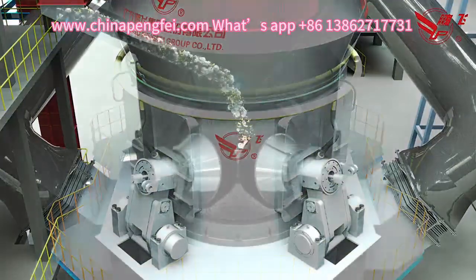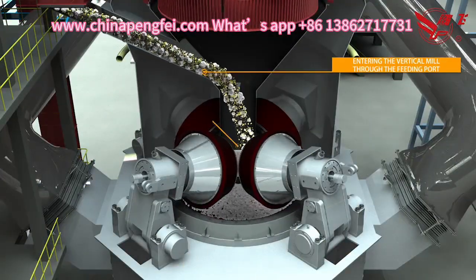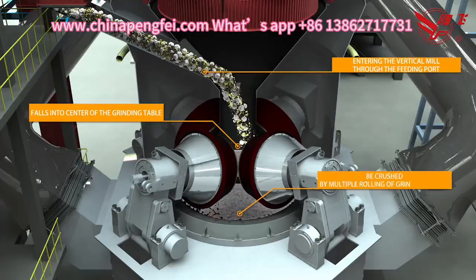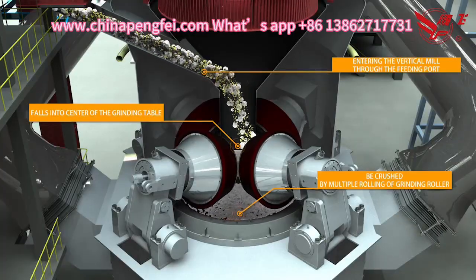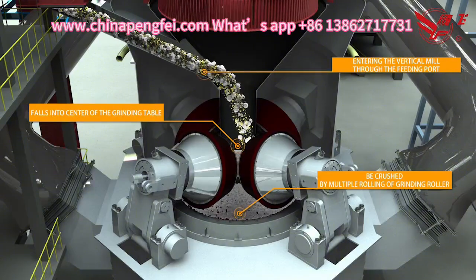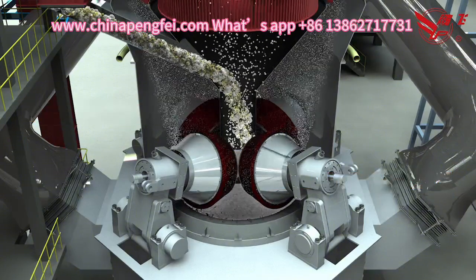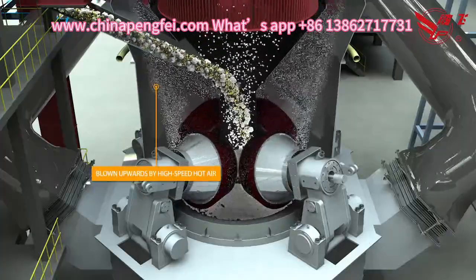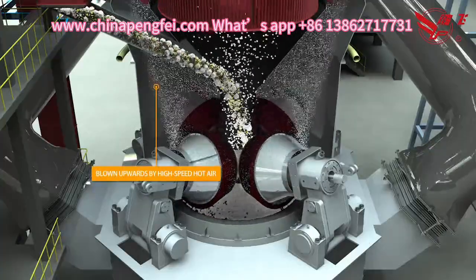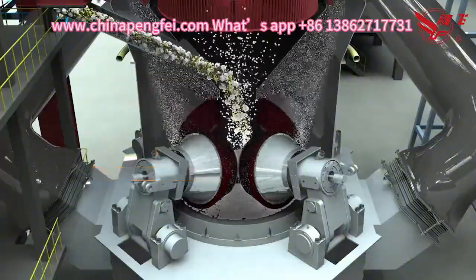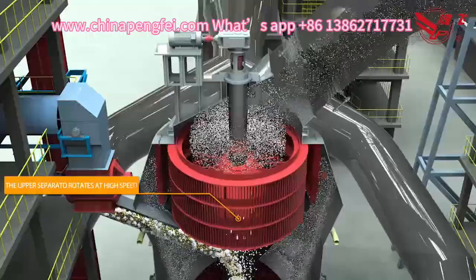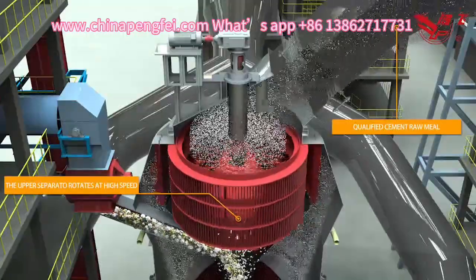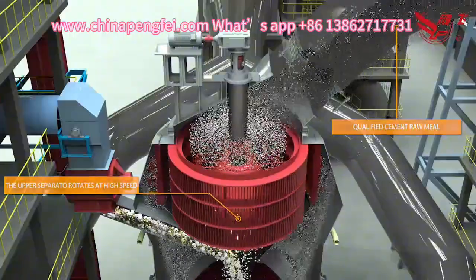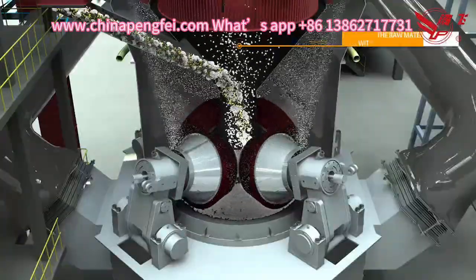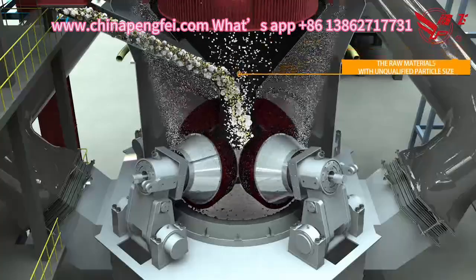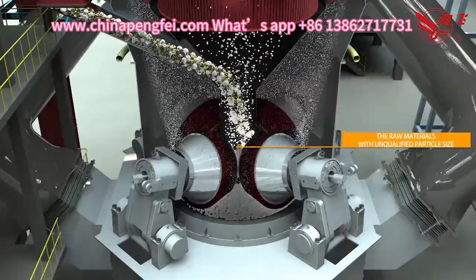After entering the vertical mill through the feeding port, the raw material falls into the center of the grinding table. Under the action of centrifugal force, the material moves uniformly towards the edge of the grinding disc and is crushed by multiple rolling of the grinding roller. The crushed raw materials continue to move towards the edge of the grinding disc until they are blown upwards by the high-speed hot air at the edge of the wind ring. When the mineral powder in the airflow passes through the upper separator, qualified cement raw meal goes out of the mill together with the airflow. The raw materials with unqualified particle size fall back from the cone hopper to the center of the grinding disc for re-grinding.